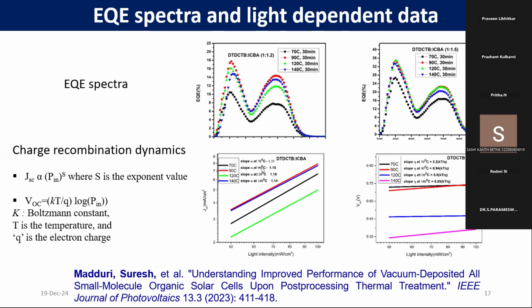After that, we need to calculate the slope values. Based on the slope value, if it is unity, I mean 1, there are no recombinations present in the device. If it is not 1, so let's say in this case at 90 degrees it is 1, but at 70, 120, 140, it is more than 1. That means at higher annealing temperatures, the device is undergoing recombinations. So we should not anneal at higher temperatures. That is the conclusion out of this. So this is how one can estimate whether the device is undergoing recombination or not. That is another characterization technique.